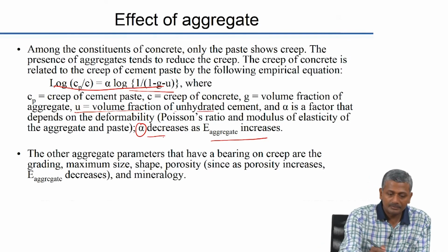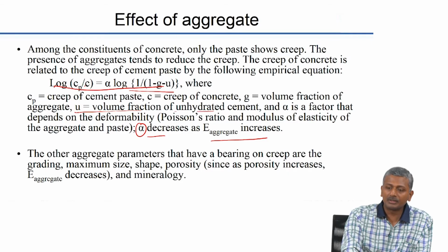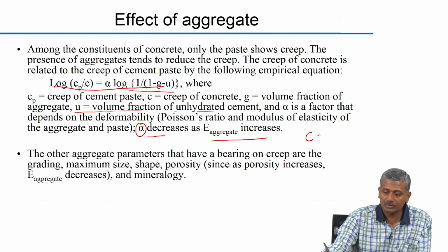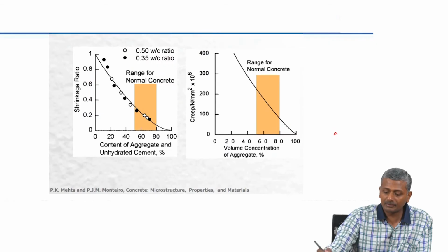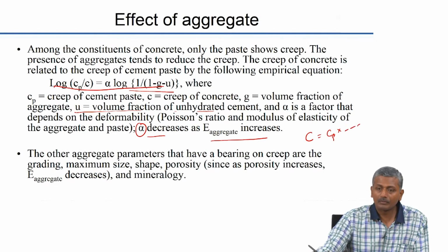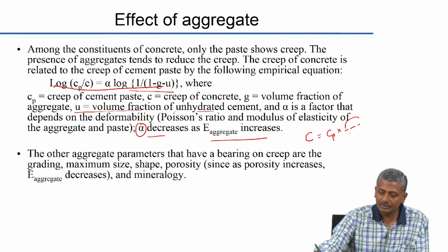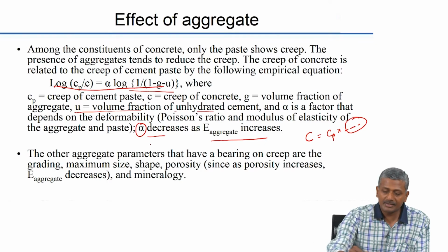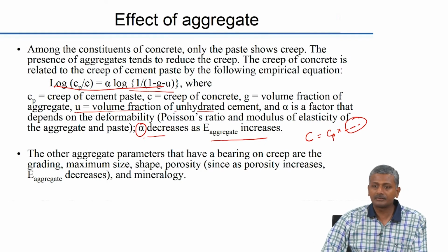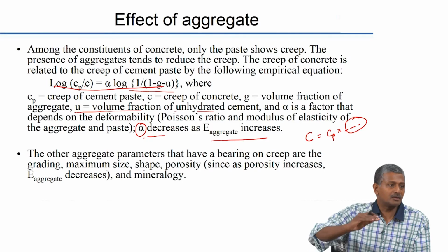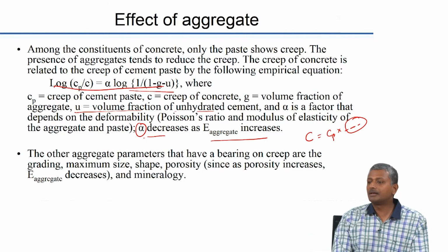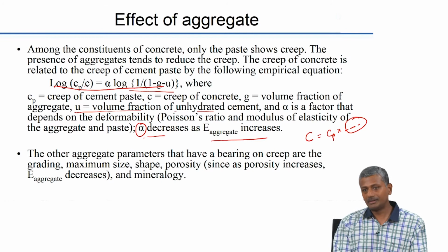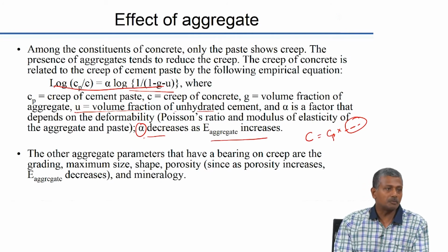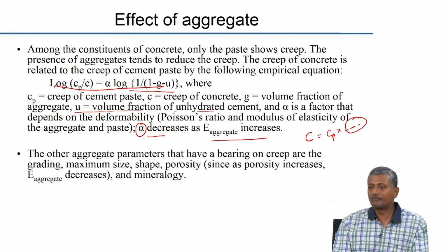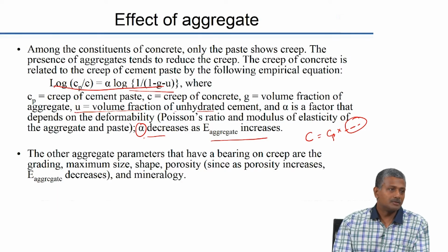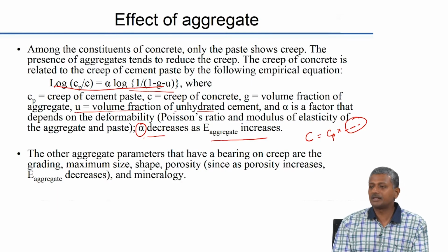In other words, if you transform this into a creep of concrete expression in terms of creep of paste, okay, whatever you get on this side will decrease as alpha decreases. That means with higher modulus of elasticity of aggregate, this alpha factor will decrease and the resultant creep of concrete also will decrease irrespective of the creep of the paste. What is the creep of paste dependent on? Obviously the water to cement ratio. The lesser the water to cement ratio, the lesser will be the extent of creep in the paste.